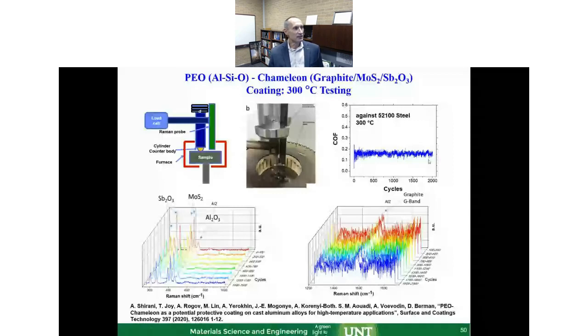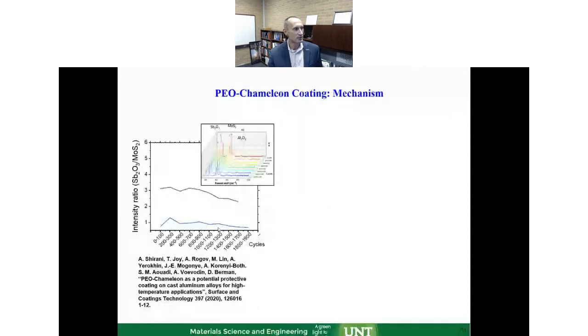Agha Shirani is a brilliant graduate student, just about to graduate, working on those materials. And he was collecting during the friction run, with the PEO and the graphite, molybdenum disulfide, antimony trioxide chameleon composition at 300 C, and he collected the Raman spectra every so often through the cycles. And we can see the evolution of molybdenum disulfide, antimony trioxide, and also the graphite. Nothing much changed on the graphite. But we definitely could see that antimony trioxide was dropping down, but the molybdenum disulfide signal was enhancing.